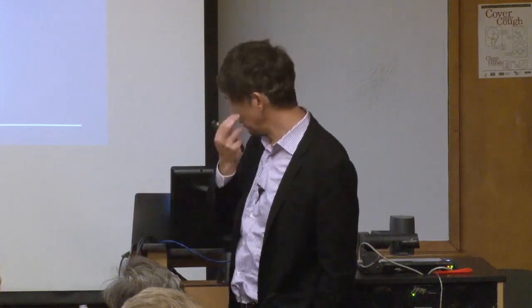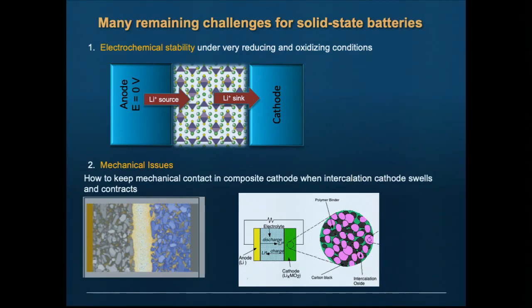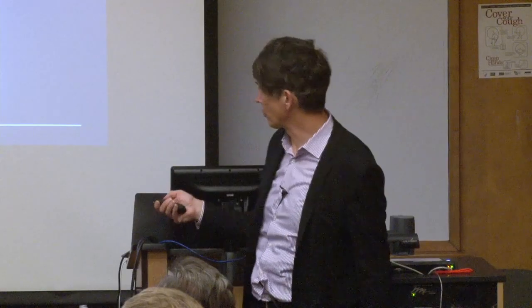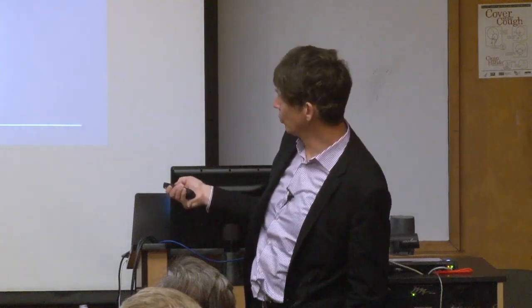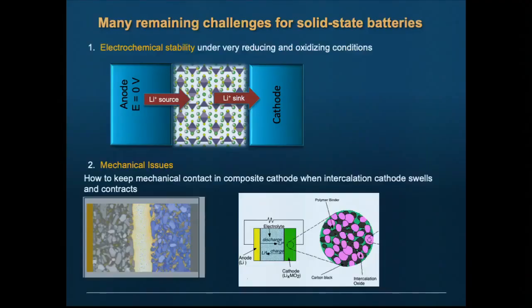But the biggest one is mechanical issues. So cathode materials swell and contract as they take up lithium. If you do this in a liquid electrolyte, the liquid just displaces and comes back. Now I'm going to have to make microstructures that are completely solid. Right? These are composite microstructures. They actually look like this. Let's say the blue thing is the active cathode, and then in between sits the conductor. But now you have to think of this as sort of a sintered or pressed composite, right? That's how this is going to look. And so this cathode is going to swell, contract, and you want to do this 1,000 times, right? You need 1,000 cycles. So the question is, how do you keep contact, interfacial contact, between these conductors and the cathode? So this is a major issue.